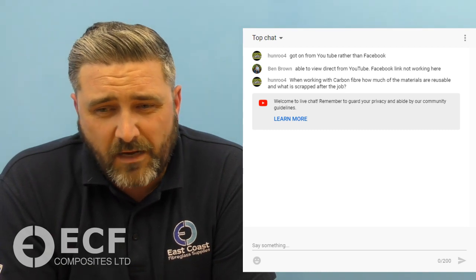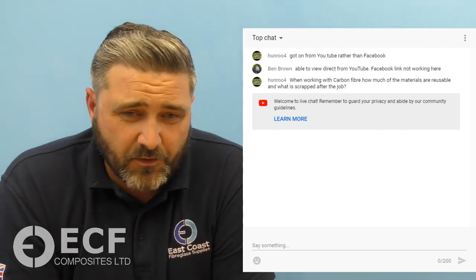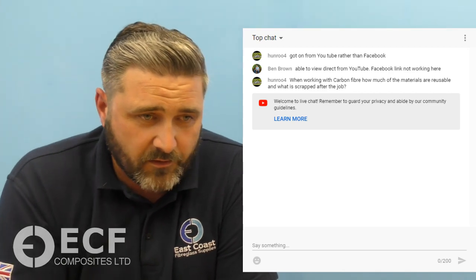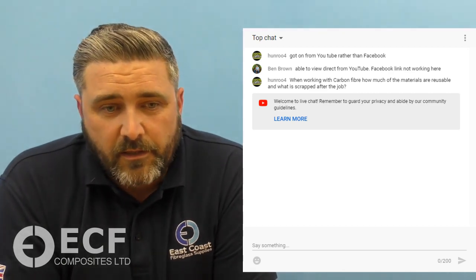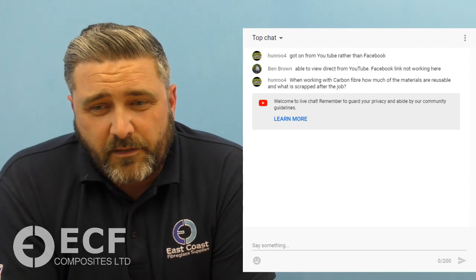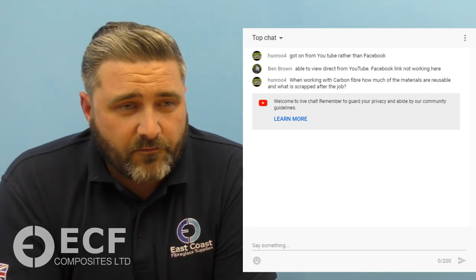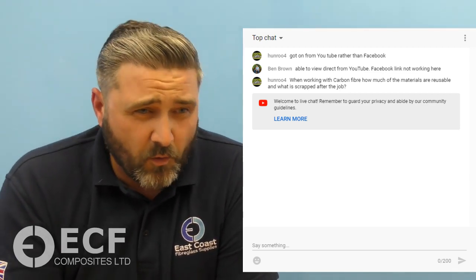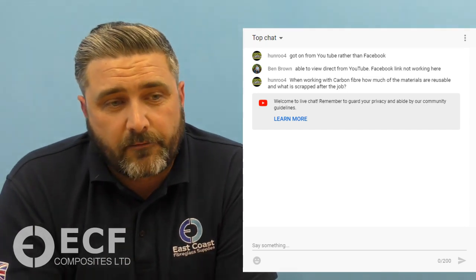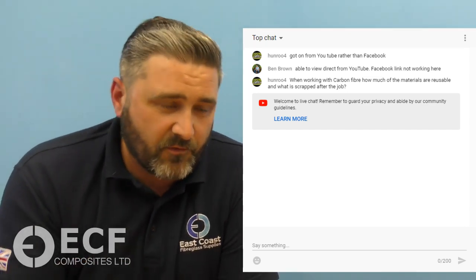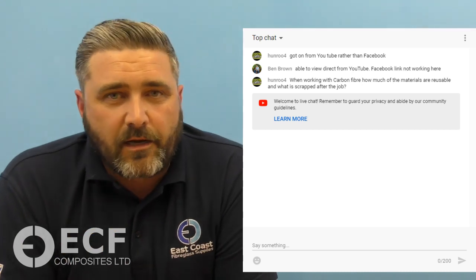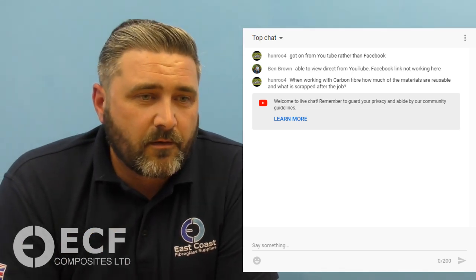If you're handling carbon, which is not the best way of doing it because you can end up with pinholes in the carbon fibre and things, but if you do tend to do them hand lay, you've got a lot less wastage, but you've got a lot more work to get it to a cosmetic level, because then you've got to sand the part down, clear lacquer it, and all that to go through.